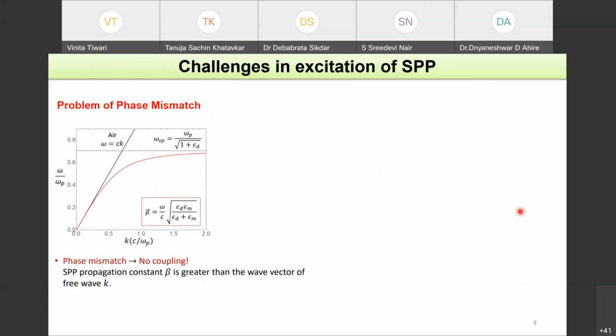Now, are we able to excite surface plasmon polaritons straight away on a metal dielectric interface? The answer is again no. The reason is there is a phase mismatch between photons and plasmons. If you look at this black straight line, this is the light line, or the dispersion curve of a photon in vacuum, omega equals ck. And this is beta. Beta is the propagation constant of surface plasmon, which is given as omega over c times square root of epsilon d epsilon m over epsilon d plus epsilon m.